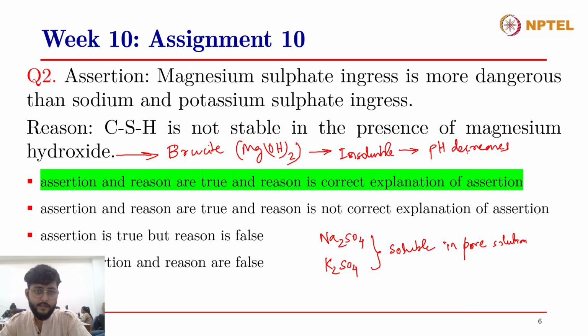And when the pH decreases, the CSH is not stable. It wants to release its calcium ions because the reserve alkalinity in the system is now reduced. So someone has to contribute their alkaline elements in order to maintain that pH. We call it the decalcification of the CSH. The CSH tries to release its calcium ions into the solution in order to maintain the pH and continue the hydration reactions. So CSH is not stable at low pH, and these low pH conditions are created due to brucite precipitation coming from the magnesium sulfate.